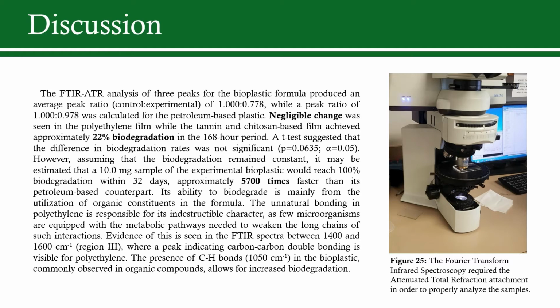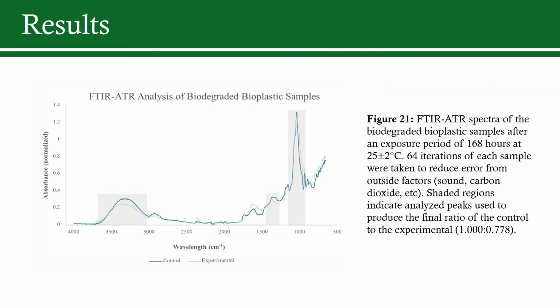The reasoning for this difference is mostly due to the unnatural bonding of polyethylene, seen in the FTIR spectra. While carbon-carbon bonds aren't unnatural, the long chains of them are, making it difficult for any microorganism to break it down. Seen around the 1050 mark, the bioplastic contains carbon-hydrogen bonds, and while they are considered stronger than carbon-carbon bonds, they are abundant in nature, making them no match for organisms.